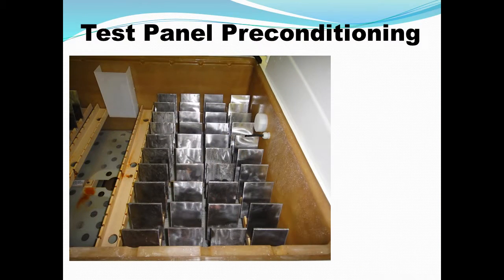In order to replicate what happens in the field, we didn't charge panels. We actually put them in ASTM B117 salt fog for 2,000 hours to replicate that pitted, rough, contaminated surface that we find in the field. And then we cleaned those corroded steel panels with a number of surface preparation methods. We assessed the retained chlorides and then made recommendations to the Transportation Cabinet on what surface preparation they should probably best use.